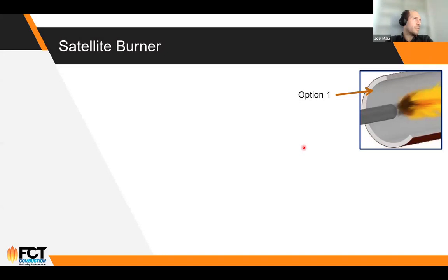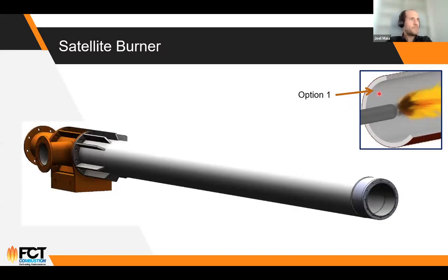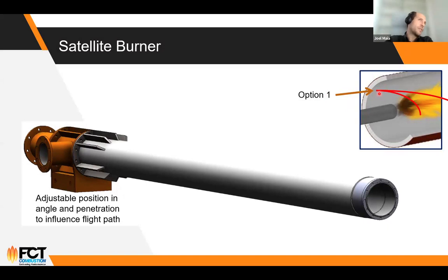If we talk a little bit about the satellite burner first, so option number one, injecting the alternative fuels on the top of the burner directly in the secondary air. This is a rendering of a typical satellite burner. First of all, this satellite burner would have an adjustable position in terms of angle, penetration, and so on. And the main reason is to influence the flight path of the particles. So you could adjust the position of this satellite burner depending if you are using a heavier particle size or a lighter particle of alternative fuel.